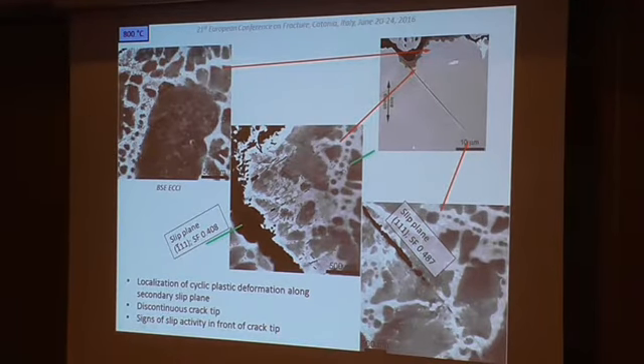We made some other observations by electron channeling imaging, where it's also possible to see some evidence of cyclic plastic localization. I'm showing these pictures because of the crack tip, where it is visible that the plastic deformation is concentrated, let's say localized, just into this slip plane in front of the crack tip, and that the crack tip is discontinuous. On this slip plane, probably voids are created, and the crack is growing by coalescence of these voids.